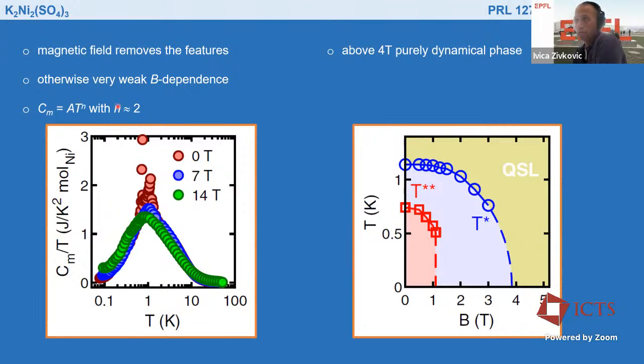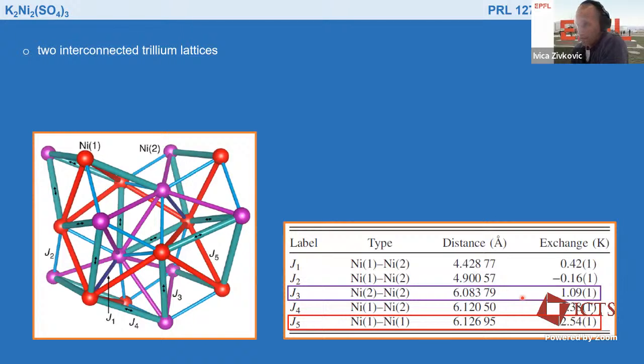And then at low temperature, if you look at the power law behavior, you always arrive at this exponent equal to 2. So there is no development of exponential behavior, which would indicate that the system develops a gap in the excitation spectrum. And then if you follow what happens with these features, you can develop this phase diagram, which leads to the conclusion that above 4 Tesla, you are definitely in a purely dynamical phase without any indications of long range order.